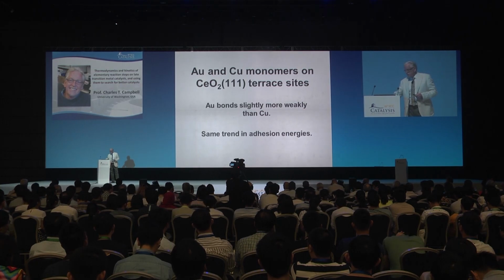I will say that when we started making these measurements for gold, silver, and copper on ceria, I was amazed because silver and gold both clearly preferred to bind to oxygen vacancies on ceria. We tested that by making more oxygen vacancies on the surface and measuring the difference in the heat of adsorption of those metal atoms. But for copper, it did just the opposite. Copper doesn't like oxygen vacancies, and I thought, why is this? The real reason is because copper is more oxyphilic, and it just doesn't like oxygen vacancies, whereas silver and gold don't like oxygen that much, and the vacancy defect is a nice place. But that was already in the literature before we made those measurements. That is the density functional theory result. So at least that level of prediction is accurate in density functional theory.